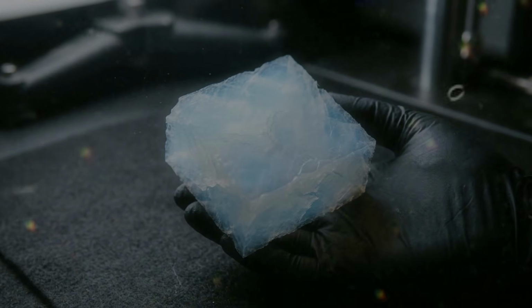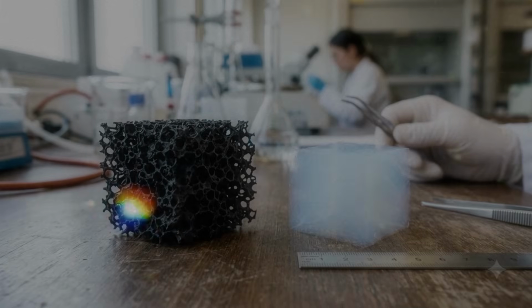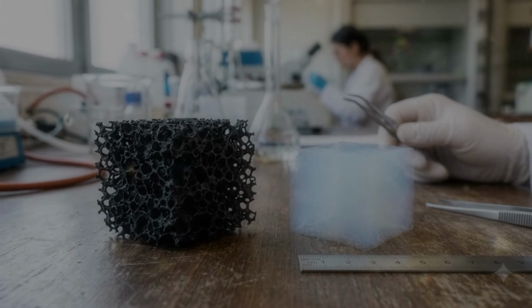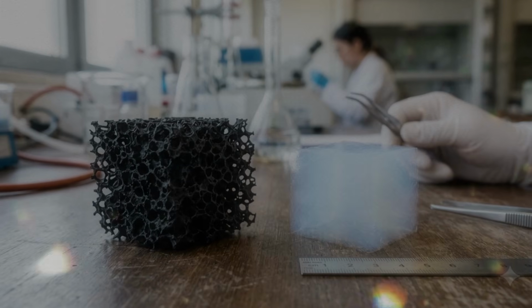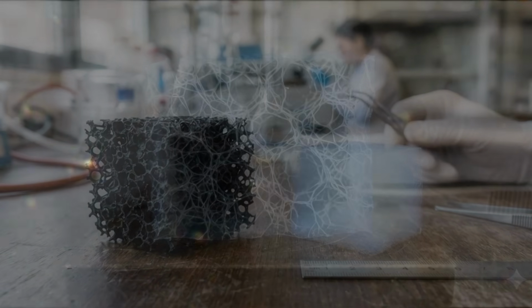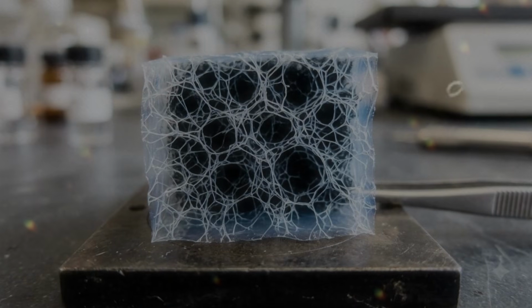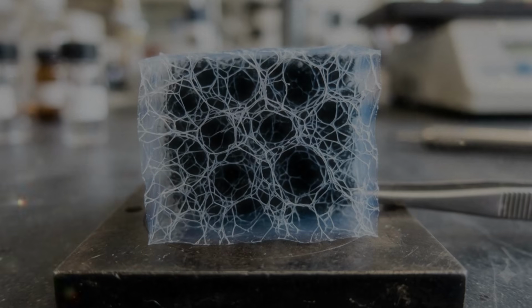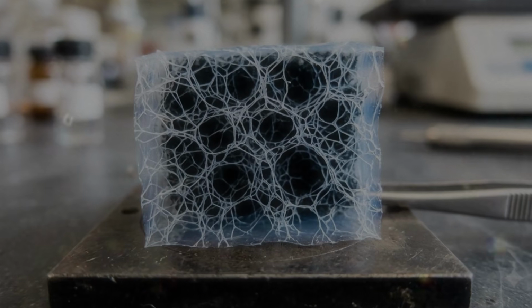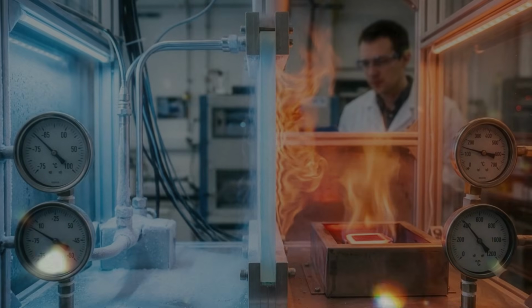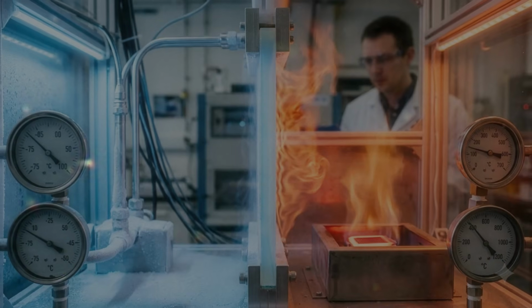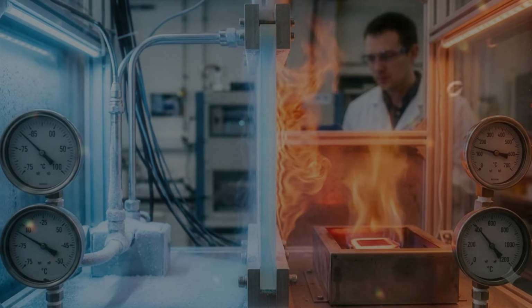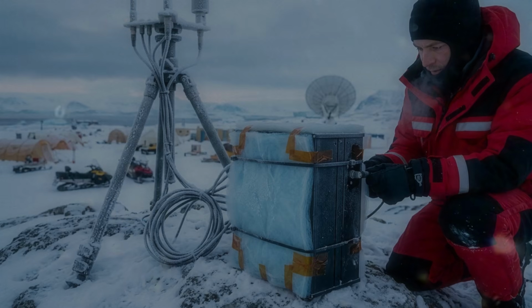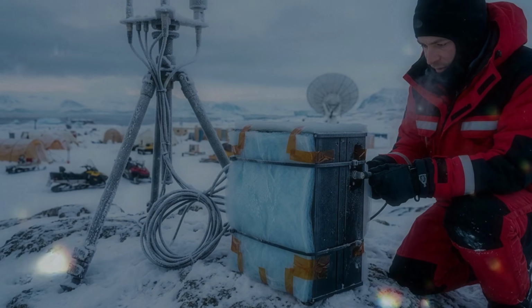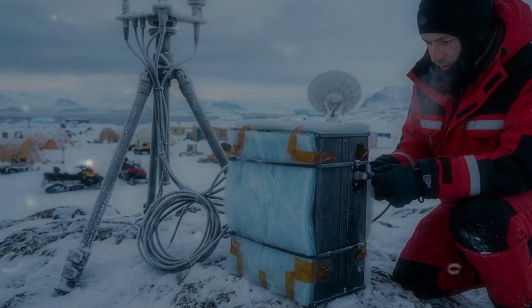During drying, different regions may shrink at different rates. Thin branches can pull away from thicker ones. The outside can dry before the center. Residual stress remains trapped inside the finished object. A sample may look intact and still contain weaknesses. A small impact can release those stresses and create a crack. Aging, reinforcement, slower solvent exchange, and controlled drying all help reduce the problem.